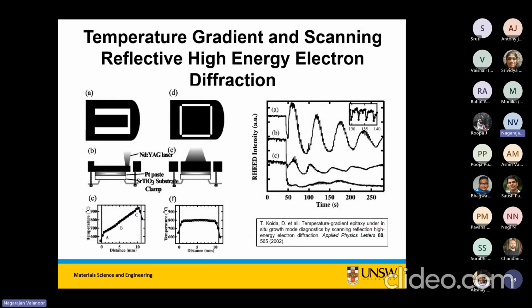The other thing that we have unique in one of our chambers is the ability to have a temperature gradient. So one of our pulsed laser chambers, because the heater is a laser diode heater. So if you're not doing thin film epitaxy, you find all of this boring, and I apologize for that. But if you're doing growth, I asked somebody over here, I think I asked Ashar, how's your heater? And he said silicon carbide coils, right? So that's a standard heater. So instead of a coil heater, think about having a solid state laser that is put onto an IR sensitive silicon carbide block, which absorbs the laser and heats because of that. Now you chop that block into pieces and you can say, I can heat this block, this block, this block with this power, and I can heat the other block with another power and so on. That gives us the ability to have a temperature gradient in a single substrate.